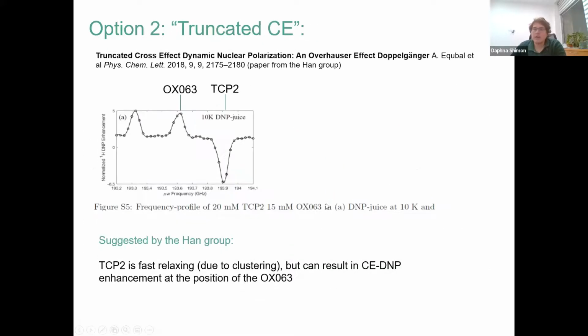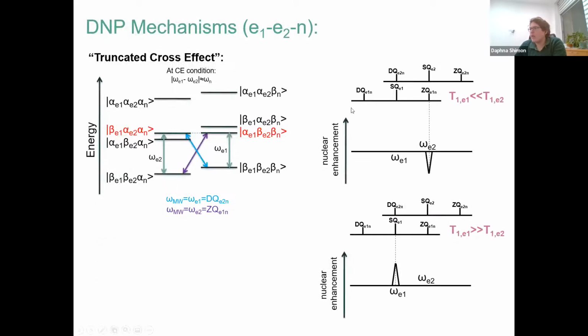And so the second option for those two peaks is the truncated cross effect, which is something that Songi Han introduced a few years ago, and they showed an Overhauser effect doppelganger. Basically, they had two types of EPR radicals in their sample, and one radical had a very fast relaxation time, and so irradiating on that radical didn't result in enhancement, but irradiating on the other radical did. And let me show it here schematically.